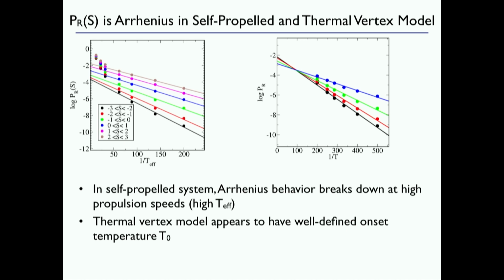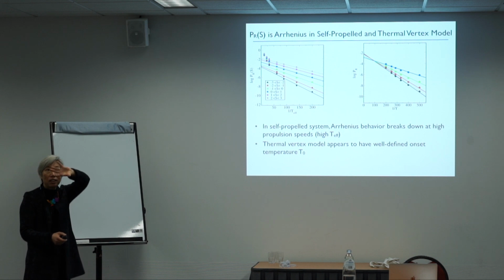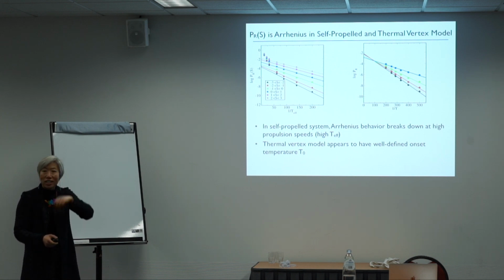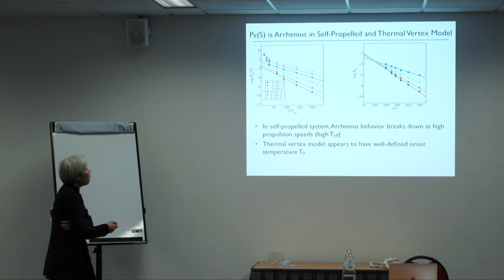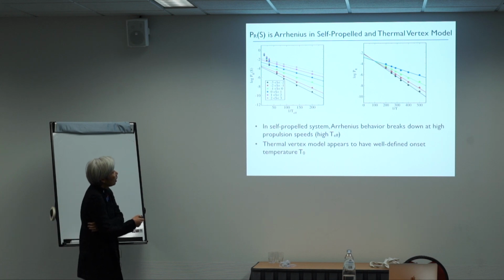The probability of rearranging is Arrhenius. If I take the self-propulsion version, I can define an effective temperature depending on the V squared and the rotational diffusion of the cells, and the drag. That works pretty well in the solid phase. The effective temperature description breaks down as you get to higher self-propulsion. But again, it's Arrhenius in this effective temperature. So this seems a very, very general result. Why? We do not understand, and we would love to.